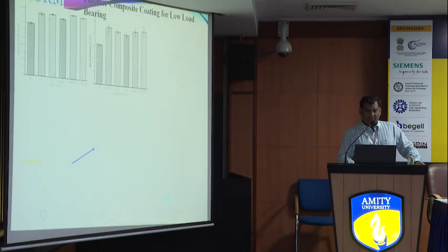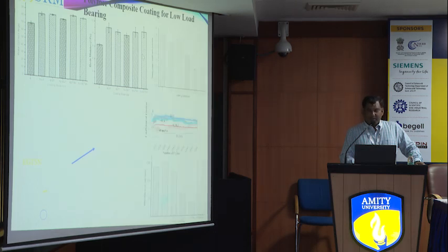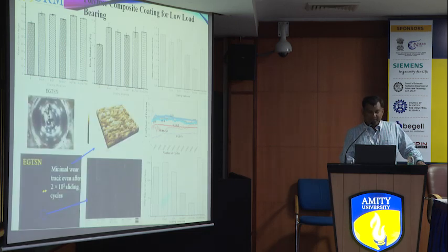After that I also added the coating and checked the water contact angle, and it is hydrophobic after adding the filler. You can also see that the elastic modulus is improved. Then the coefficient of friction: EGTSN means epoxy graphite, and SN is the base oil, a group 5 SN150 that is used in automobiles. And we can get 0.1 without any lubricant. I ran these tests up to 24 hours, and only after 24 hours did I take the data that is presented. So approximately why is it like that?